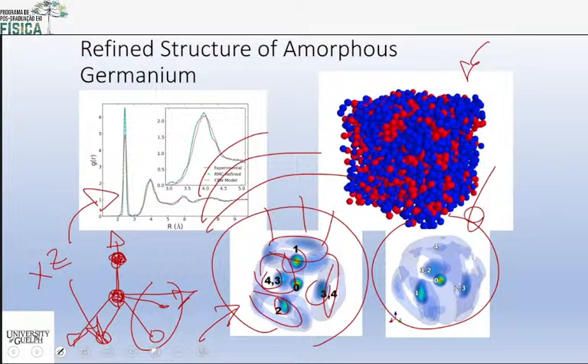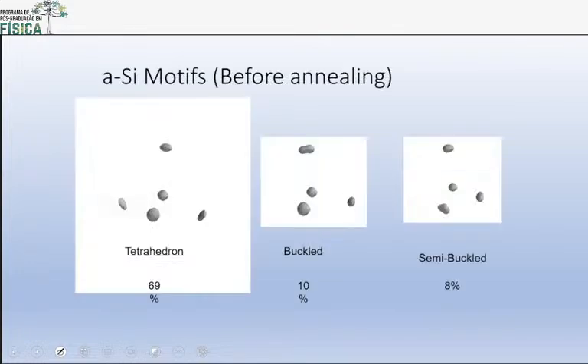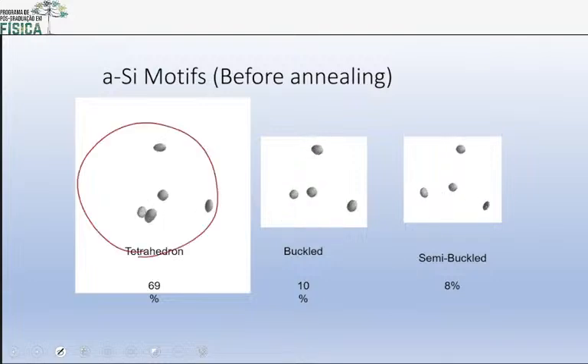So I'm almost done with this one. What we did was we were able to figure out that the models had different motifs, let's call them, and that the very, very common 69% were these perfect tetrahedra. But the rest of the model was finding what we call buckled shapes, sort of a 3 coordinated silicon in the middle with 3 atoms hovering around it. So it wasn't really like the tetrahedron minus an atom. It was a little different than that.